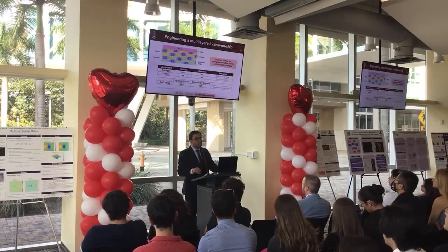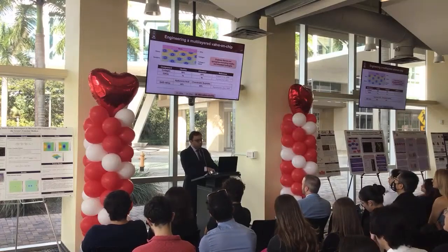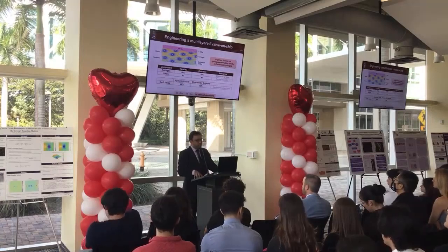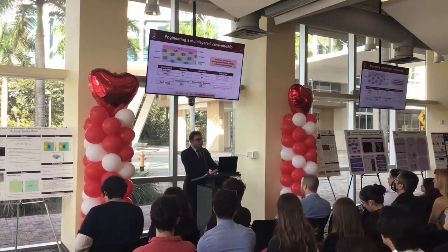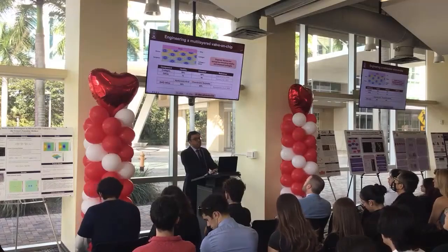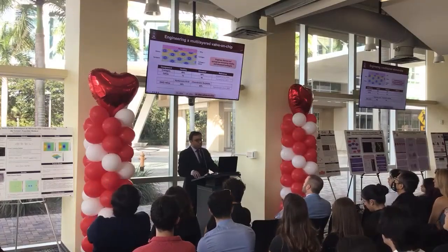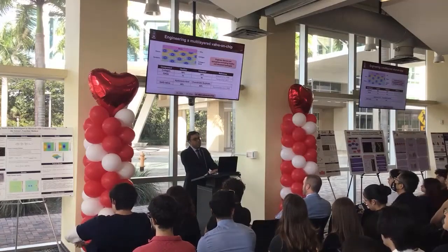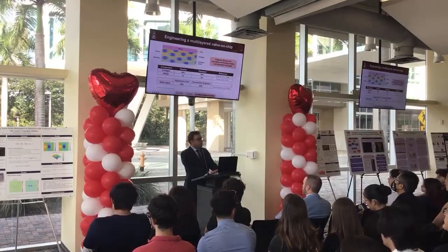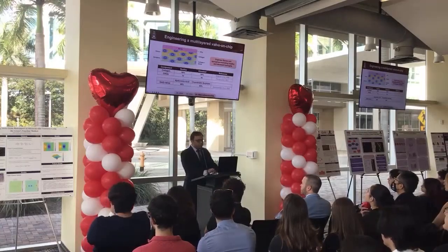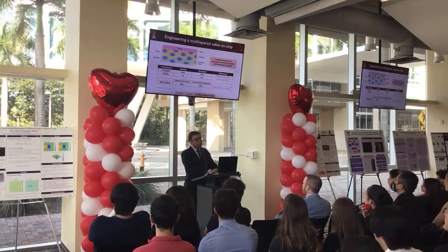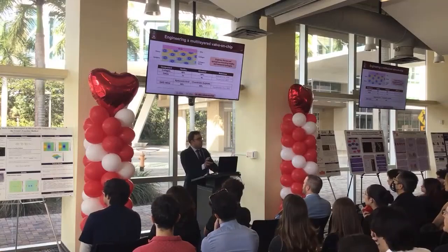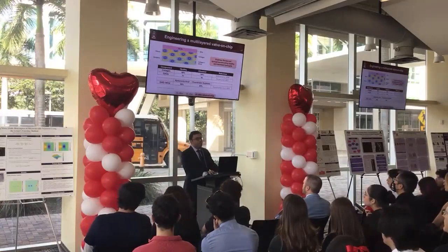To effectively study disease, it's also important to mimic both the healthy and the disease composition of the extracellular matrix of the valve leaflet. And so we did that by increasing or simulating the enrichment of glycosaminoglycans that exists during early disease progression, as shown here in the table. So we constructed a disease hydrogel that had 4 times the amount of glycosaminoglycan compared to the healthy hydrogel. And then, since these were methacrylated, we were able to use UV cross-linking techniques to polymerize this gel and create a hydrogel for growing these cells.